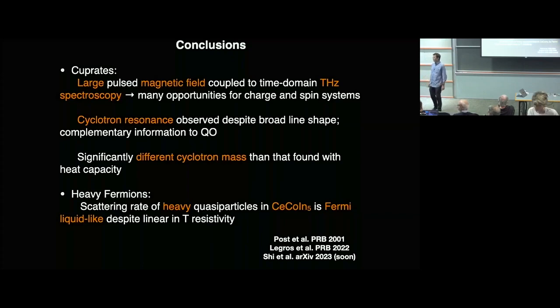Perhaps a naive question about the second part. You talk about frequency-dependent tau, but at the end of the day, you looked at resistivity, which means it's a zero frequency result. So you are attributing the change between T square and T behavior to m star, which by itself depends on temperature, which gives you 1 plus lambda at omega equal to 0. It's the same factor that appears in specific heat. So shouldn't you expect that specific heat should go as T square in this situation? T times 1 plus lambda goes as T, so...